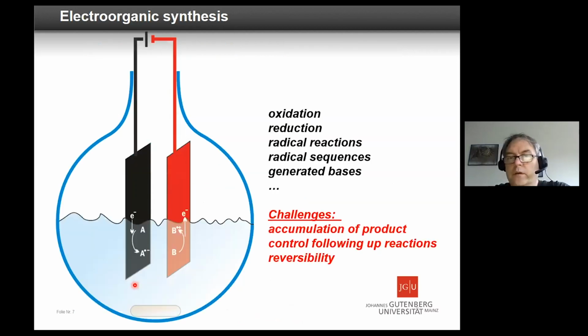What can you do with electrosynthesis? Oxidation and reduction is more or less trivial, but you can start radical reactions or sequences, or generate bases, because you make a radical anion, and this could have a basicity like butyllithium. But the problem for electrosynthesis is often you have to accumulate your final product. That means here you reduce, here you oxidize. In the worst case, you shuttle here, and then you have a full reversibility. Then you have to separate these kinds of compartments. And one way is to design the following-up reactions in a way that you do not have reversibility.